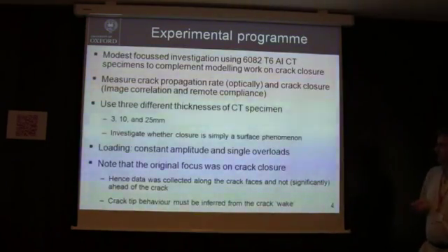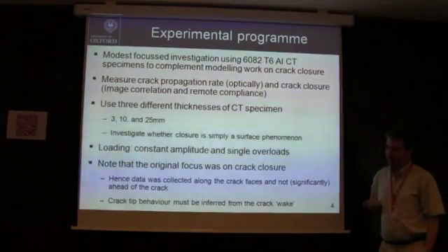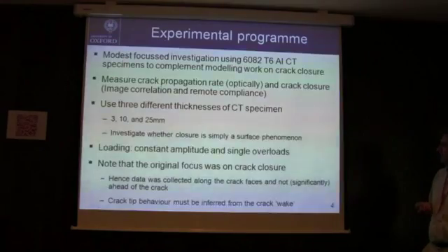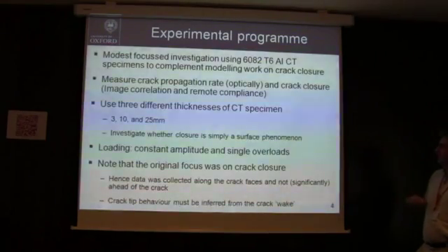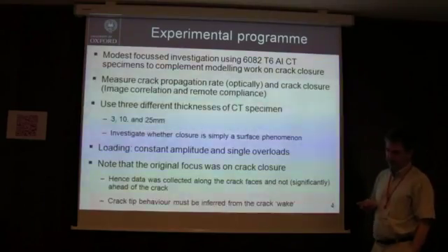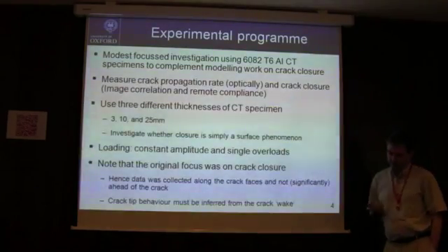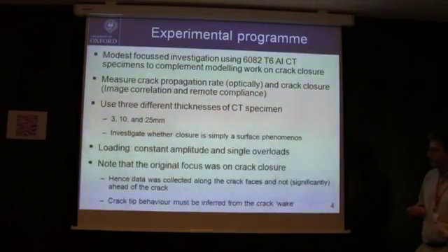In fact, I think in many ways the experimental work turned out to be a bit more significant than the modelling work, but that's how things go. He measured the crack propagation rate optically, and measured crack closure both with a conventional strain gauge, looking at compliance, and also optically using digital image correlation. It's those results that I want to think about today.